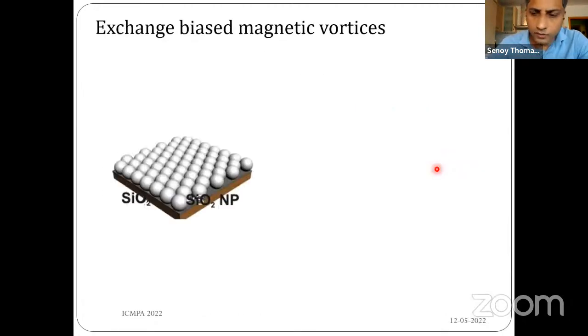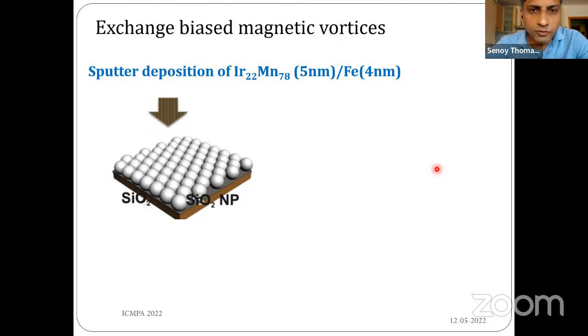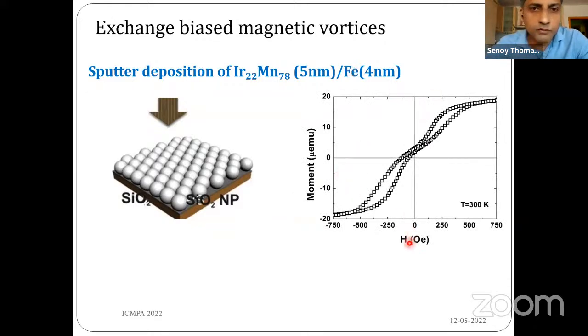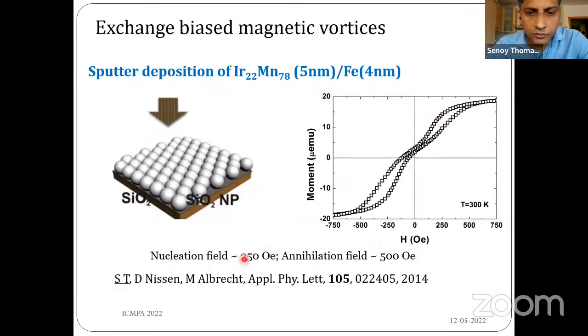Then we coupled these iron nanocaps with an antiferromagnetic iridium manganese. 5 nanometer iridium manganese was deposited onto the top of this 4 nanometer iron, thereby coupling the magnetic vortices with the antiferromagnetic iridium manganese, keeping in mind that coupling with an antiferromagnet would be a useful tool to stabilize the magnetic vortices in an external field. Here is the moment as a function of field curve for such an exchange bias system. One could see that the nucleation field is now increased to 250 Oe, and the annihilation field is now increased to 500 Oe, which means that the coupling with an antiferromagnet really provides field stability to the magnetic vortices.